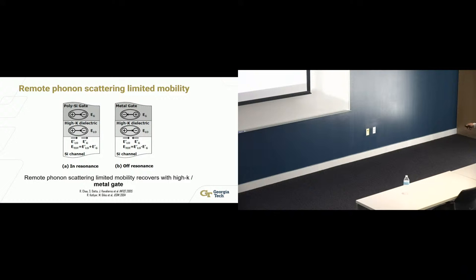It turns out this remote phonon, you can think of as an oscillating dipole. This is the in-plane mode that we were particularly worried about. But in a polysilicon gate, because it is depleted when you apply a positive gate voltage, there's a depletion region here, and you end up with a phase lag in the electrons sitting in the polysilicon gate. This is a collective phenomenon. You can think of a bunch of electrons in the gate acting as a plasmon, not like individual electrons. Because of the low concentration of electrons in the polysilicon gate, the dipole had a phase lag. So they were adding on to the high-K dielectric dipole, and the net effective dipole that the electrons were seeing was enhanced.